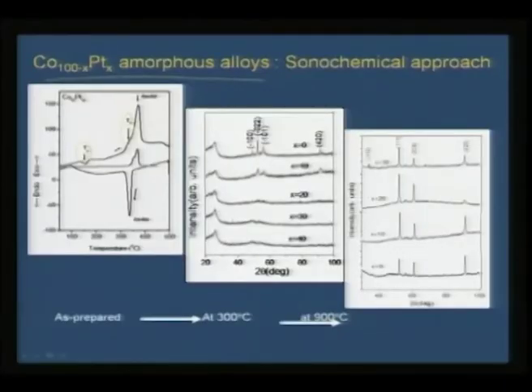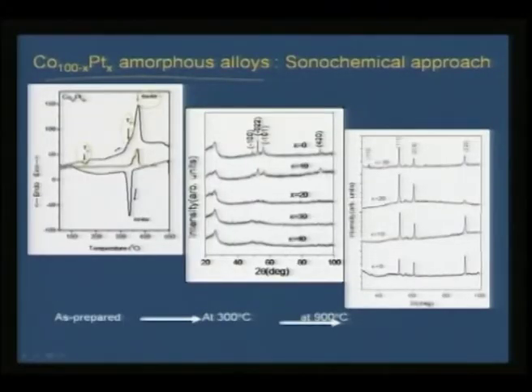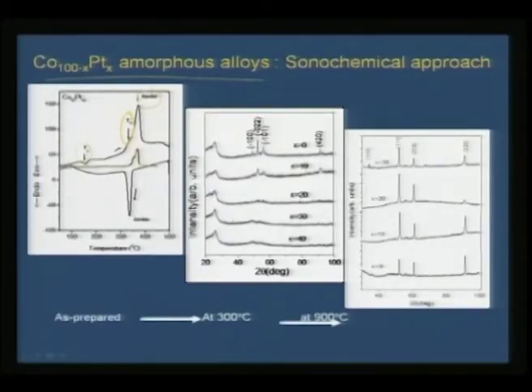Now one of the beauties of this DSC curve is that it tells us whether this is a reversible transformation. First is the glass transition and then the crystallization, then you see the FCC to FCT conversion, and when you reverse it back, this FCC to FCT now reverses back to FCT to FCC. So this is a reversible conversion, but once you have crossed through this crystallization temperature, on the second run you see that this crystallization has become smaller, and in the reverse you do not see anything. So the FCC to FCT conversion happens beyond 400, and this is a reversible conversion in the first cycle, but once it is crystallized then you do not see this reversible conversion. So this is the essential feature for any usage of this cobalt platinum nanoparticle. Therefore you have a governing principle there, you can't go beyond 300 degrees C.